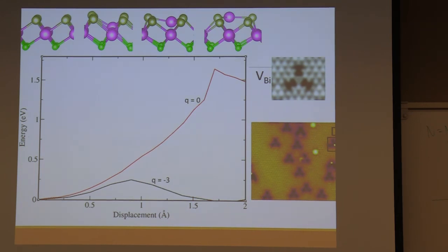Prevent defects from forming? Keep it at a very low temperature. You would have to somehow charge it. Yeah, to mess with the potential, you'd have to charge it. One can view the reason why these defects form is because they want to get rid of that charge on the surface. So if you put different defects on the surface, let's say you didn't like these defects, but you had another acceptor in mind that you wanted to put on the surface, then that would be fine. You decorate it with a bunch of external acceptors, then that would lower the Fermi energy, and then these defects wouldn't form. So that would be a way to prevent these kinds of defects, but you've got to somehow manage it.